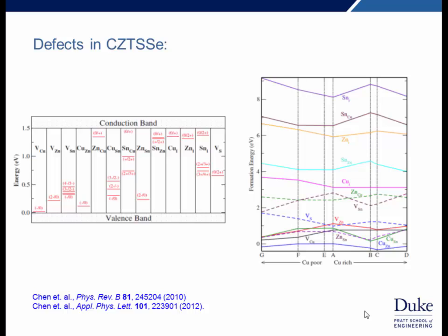This can be examined using density functional theory, looking at formation energies and energetic positions of these defect states in the band gap. And what's clear in these calculations here is that there are a number of defects that have low formation energy. In fact, in this particular calculation, the copper on zinc anti-site defect has negative energy, which would mean it forms spontaneously. And in fact, if you look at the composition of these films using neutron diffraction or resonant X-ray diffraction, one finds that there's macroscopic amounts, on the order of tens of percent, anti-site disorder between the zinc and the copper. So clearly there's a large amount of disorder in these materials.